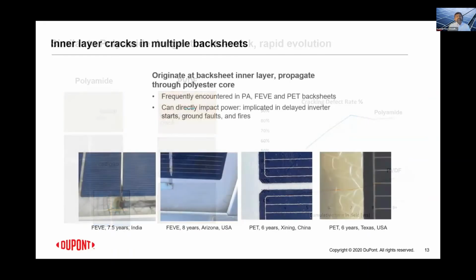The next type of defects that we are seeing is the inner layer crackings. So the earlier one was the cracking of the outer layer, which is probably one of the most egregious defects that a backsheet could have in the field. In this case, these inner layer cracks actually originate at the inner layer, as the name implies, and then they propagate through the polyester core, which typically forms the core layer of a backsheet. We have seen this frequently in polyamide, some coated backsheets, FEVE, which is a fluorinated coated backsheet, and several PET-based backsheets.